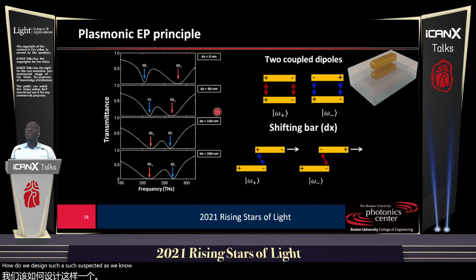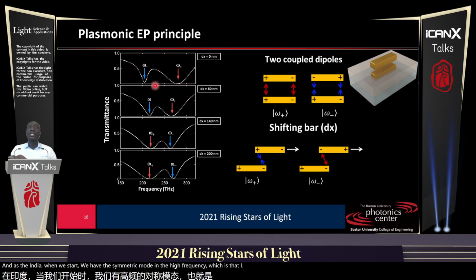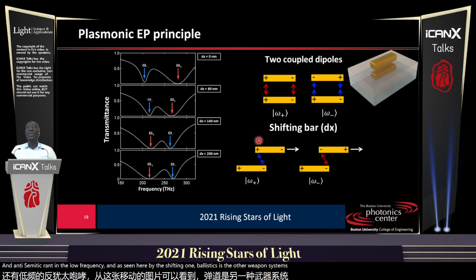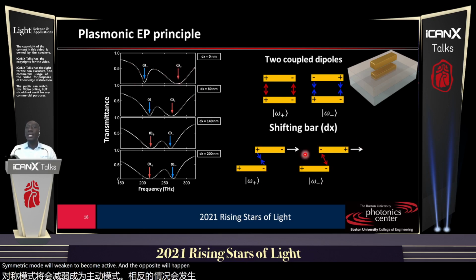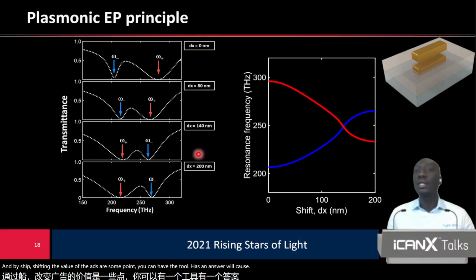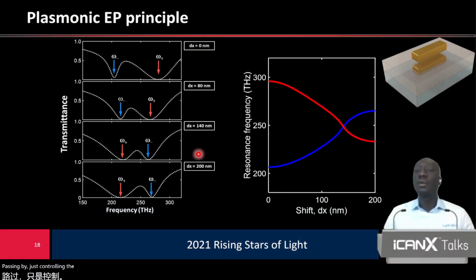As we know, when you pair two gold bars in close proximity, you hybridize the plasmon mode into two modes of opposite symmetry. Oscillating in phase, you have a symmetric mode. Out of phase, you have an antisymmetric mode. And we know that the spectral position of these modes can be tuned by spatially shifting one bar with respect to the other. As seen here, when we start, we have the symmetric mode at high frequency, which radiates more, and the antisymmetric mode at low frequency. By shifting one bar with respect to the other, the repulsive character of the symmetric mode will weaken to become attractive, and the opposite will happen in the antisymmetric mode. By continuing to shift the value of dx, at some point the two resonances will cross, which shows that you can have resonant crossing by just controlling the shift of the two bars.